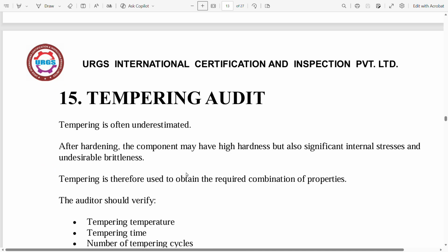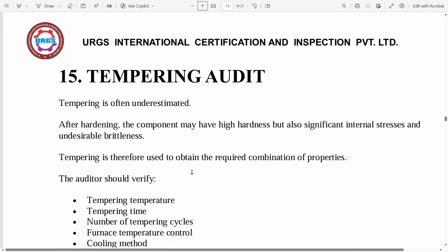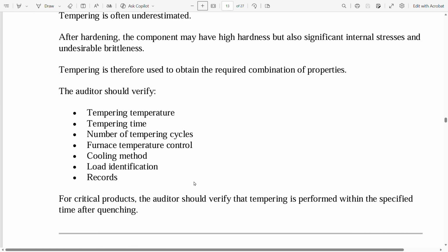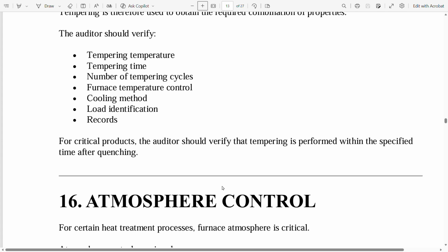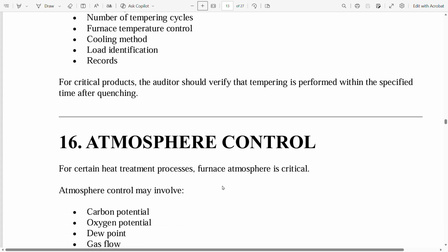Then 15th is tempering audit. Tempering is often underestimated. After hardening, the component may have high hardness but also significant internal stresses and undesirable brittleness. Tempering is therefore used to obtain the required combination of properties. The auditor should verify tempering temperature, tempering time, number of tempering cycles, furnace temperature control, cooling method, load identification, records. For critical products, the auditor should verify that tempering is performed within the specified time after quenching.